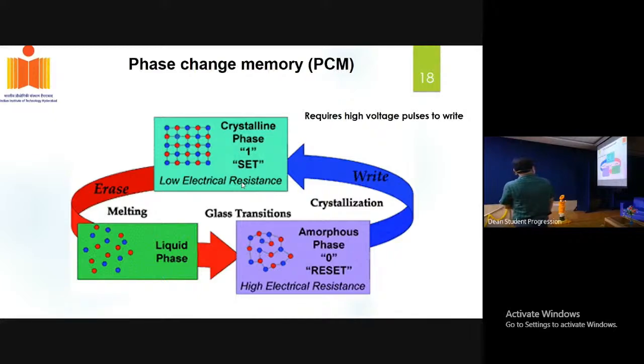And then by applying high voltage pulses, by melting the sample, again you can go to the amorphous state. So it's basically toggling between the amorphous state and the crystalline state. By the application of voltage pulses, you can get the set state and the reset state. The set state means going from high resistance state to low resistance state, and the reset state means going from low resistance state to high resistance state. By repeated application of voltages, you can read the amorphous state as 0 and the crystalline state as 1. So you can repeatedly toggle between the 1 state and 0 state. 1 state means low resistance state, 0 state means high resistance.